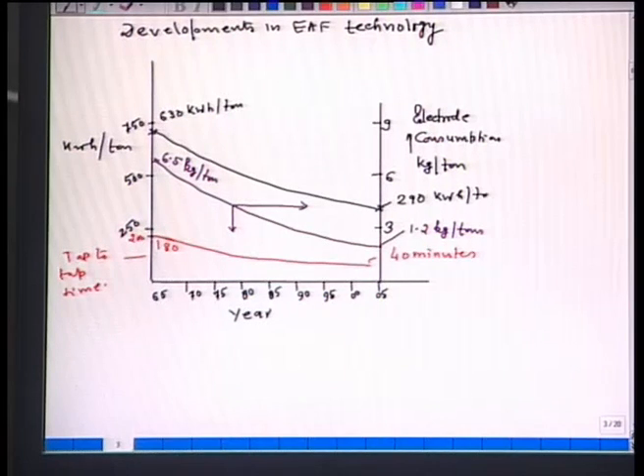As regards power consumption, which was here say at around 630 kilowatt hour per ton, you can imagine the huge power consumption in the 60s or 70s, it has continuously decreased to a value of around 290 kilowatt hour per ton.